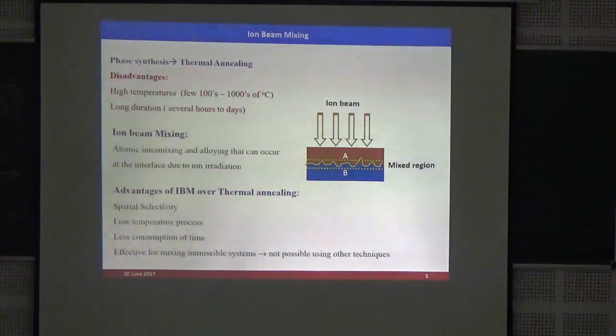The ion beam you are using, does it also get trapped in the metal or not? Yes, sir. Then you have a secondary phase or some different phase. So for that we have to choose very carefully. Like if suppose my materials are nickel and bismuth, if I know that the range is less than the thickness of both the layers, then I have to use the same element, like either nickel ion or bismuth ion, or I can use inert gas elements like argon, krypton. Otherwise the energy can be such that it will go much deeper into the substrate and sit there.